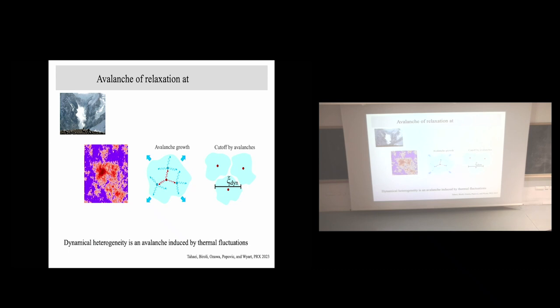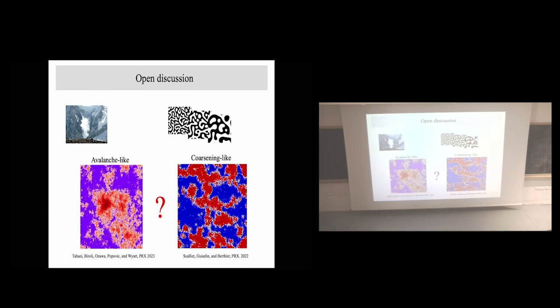Again, so what you are saying is that this is not related to the energy barrier. In our model setting, we don't have an energy barrier, so if you plot the relaxation time, it's purely Arrhenius. But it's just a model, and in order to reproduce non-Arrhenius behavior, we need to elaborate the model, for example, with temperature dependence of the energy barrier. You know that the elastoplastic model has many arbitrary rules, right? But this is within this model. So this is an open question.